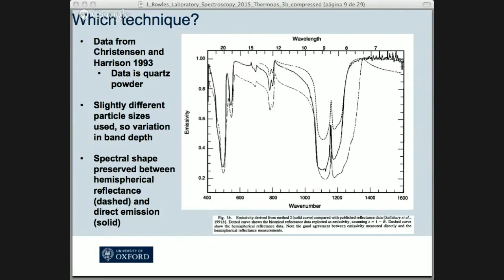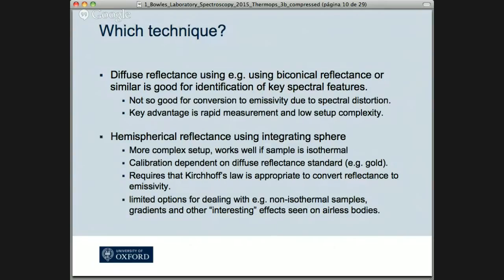So realistically, the two best methods, unless you want a quick look at your data to find out rough positions of bands, are to use something like an integrating sphere, or to measure the emission directly. The hemispherical reflectance is good, but we have to assume that one minus reflection is equal to emissivity. That means you've got limited options for dealing with non-isothermal samples. And of course, when you go to airless bodies such as the moon or an asteroid, it's going to become kind of interesting, and that's going to generate a lot of spectral weirdness that we have to somehow deal with in our analysis.